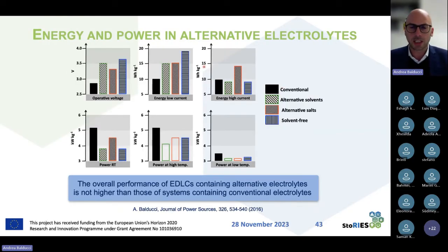Because what we are now seeing in this picture is, for example, that when we are using this electrolyte in combination with activated carbon, and this is the picture from before, we can increase the operative voltage. And then what we can see is that when we are applying lower current, the energy that a supercapacitor can deliver, this is a lab scale system, but nevertheless, is significantly higher than that of the state of the art.